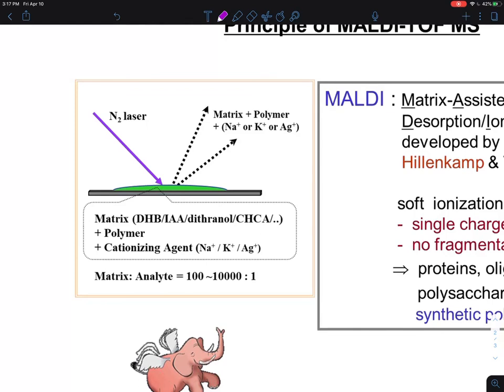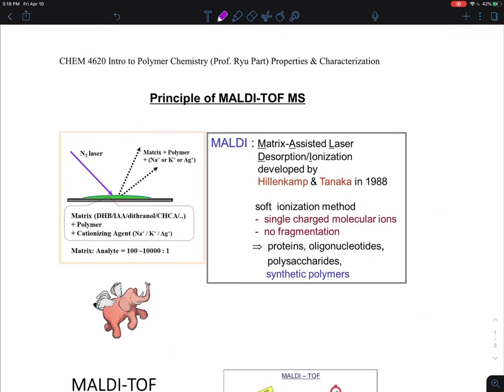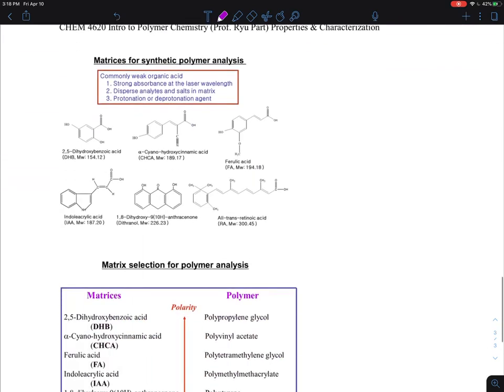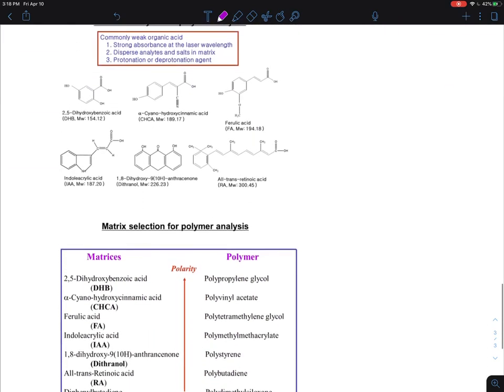How to make the right cocktail for the MALDI-TOF experiment has been not in the realm of science, but more in the area of art. The rule of thumb is polarity matching. You want a polymer with similar matching polarity.